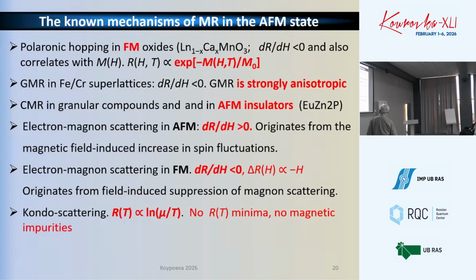First of all, I list here the known mechanisms for you to remember, which can appear in ferromagnetic and antiferromagnetic materials and can be responsible for the magnetic resistance. The polaronic hopping in oxides gives you exponential dependence, which here is inapplicable because we have semimetals and no oxides and no ferromagnetism in total. Giant magnetic resistance is the most favorable and the most used even in applications, the magnetic heads. But this magnetic resistance is strongly anisotropic. It is the most pronounced when the current flows across the layers of, say, iron and nickel. And so this is not the case.